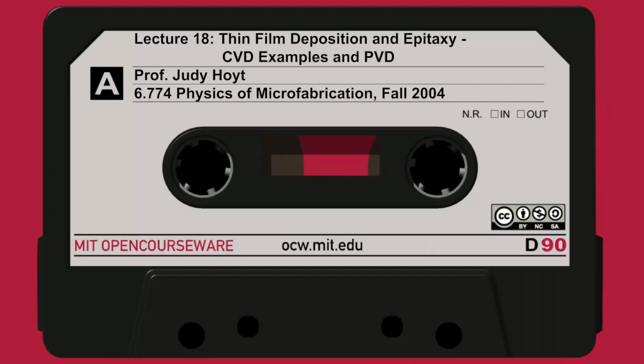That's right around the amorphous to crystalline phase transition. So if you go below 580, the film is pretty much amorphous primarily, although it will contain some small polycrystallites, which sometimes people call seeds. So 580 is the magic number. You go down below that, you get amorphous material as deposited. You go above that, and you get polycrystalline material.